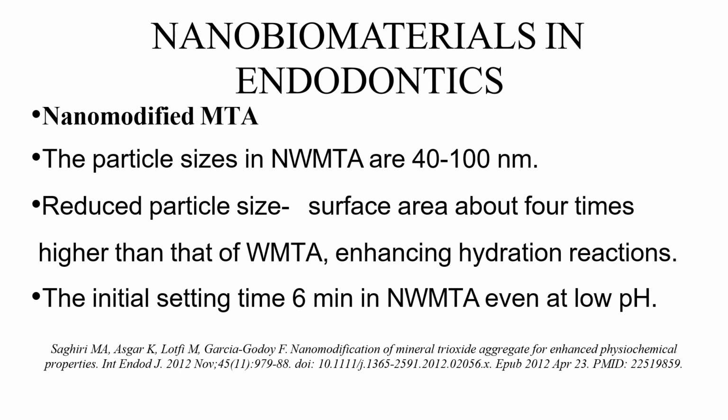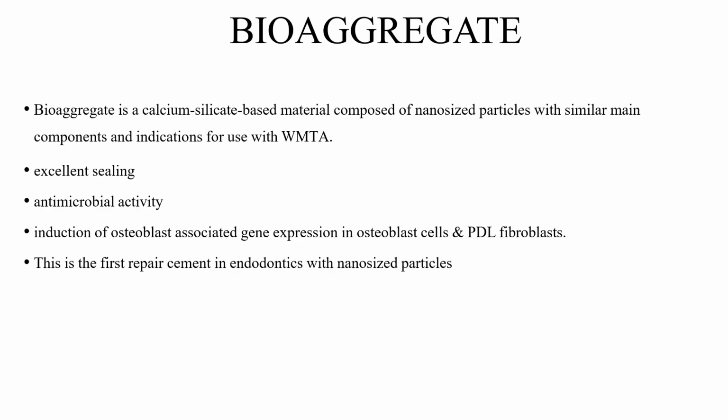Nano biomaterials in endodontics. Nano-modified MTA has a particle size of 40 to 100 nm, reducing particle size and increasing surface area about 4 times when compared to white MTA, enhancing hydration reactions. Initial setting time is 6 minutes, and it sets even at low pH. Coming to BioAggregate, it has excellent sealing and antimicrobial activity. It is the first repair cement in endodontics with nano-sized particles.